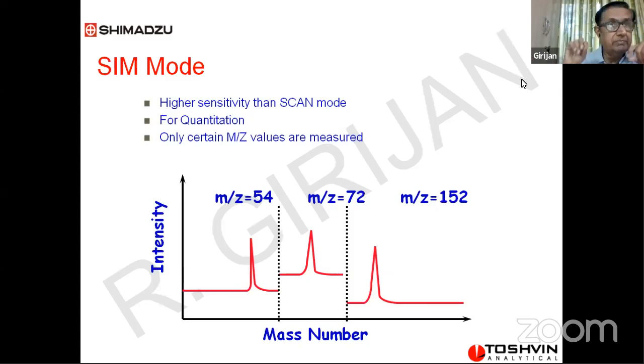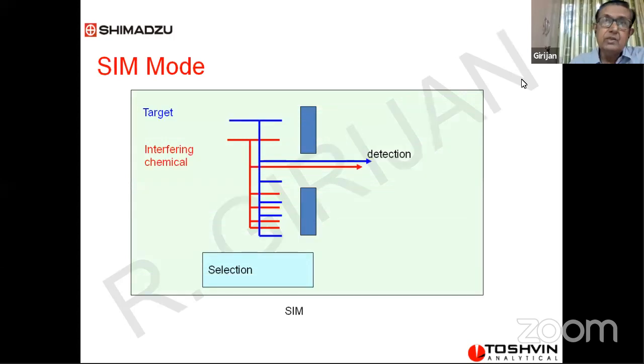We are keeping a different ratio which can monitor only 72 in the second compartment. And we are fixing the ratio which can see only 152 in the third compartment. So there are three different DC/RF ratios fixed, one for each of the selected fragments. So when other fragments are coming, the ratios are not there, they will be totally blank. So the detector will be able to monitor these three selected fragments, and based on this, you can get a very accurate quantitative result. So SIM mode is to be used for quantitation and scan mode is to be used for qualitative analysis.